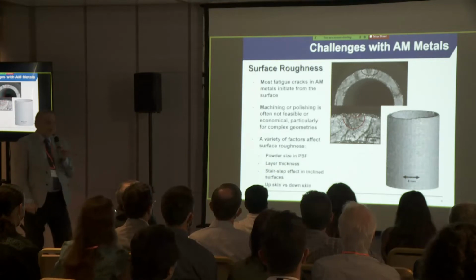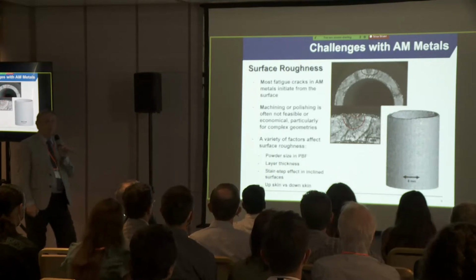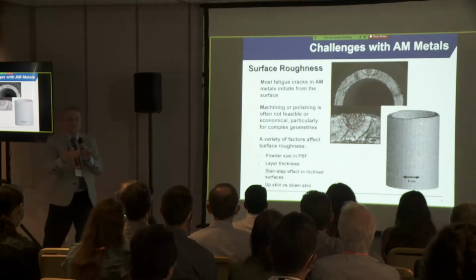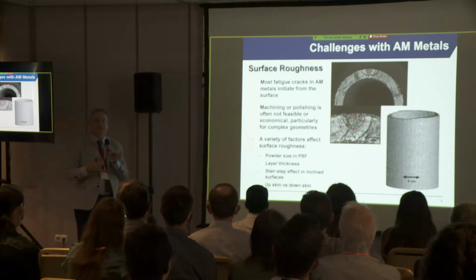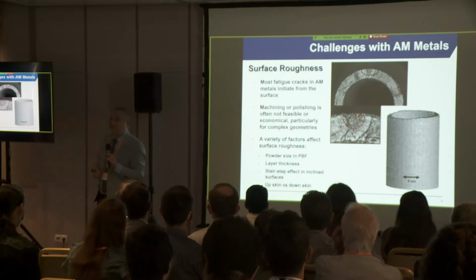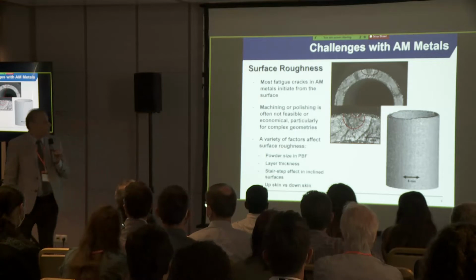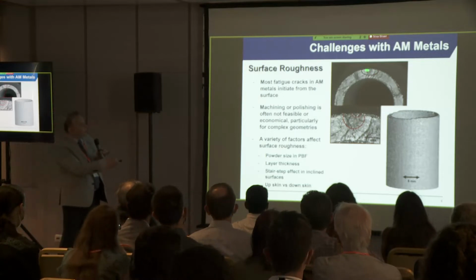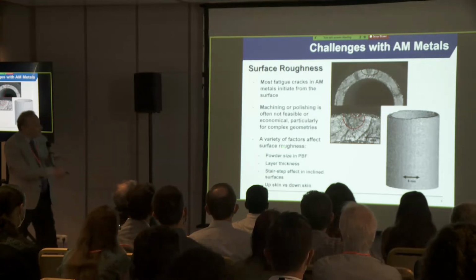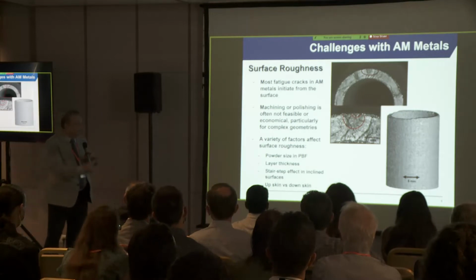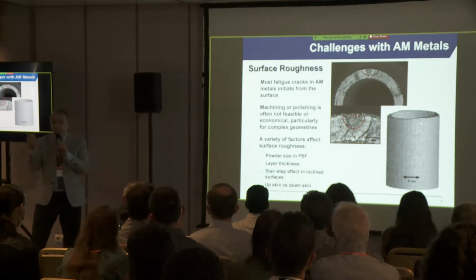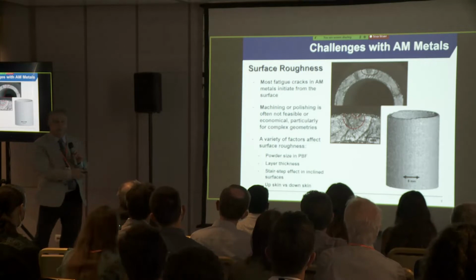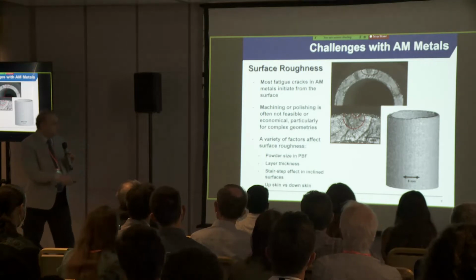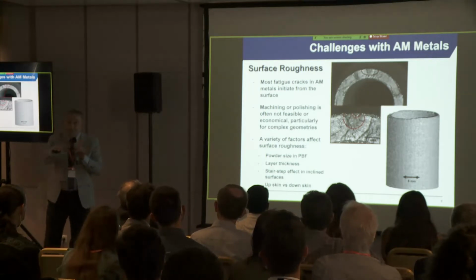Surface roughness is another big challenge. When you deal with as-built surface in additive manufacturing, nearly always fatigue fractures start from surface. And this is an example. Surface roughness depends on a variety of factors, including what size powder you start with, including what layer thickness you are using, and a stair-stepping effect, and so on.